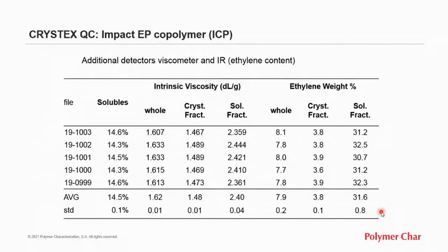As I said, in addition to quantifying the soluble fraction, the intrinsic viscosity for the whole polymer, the soluble, and the crystalline fractions are measured. For this sample, we have replicate analysis for the same sample. And we can see how the intrinsic viscosity for the soluble fraction is 2.4, which is larger than the intrinsic viscosity of the crystalline fraction or even the whole. So that may be important in some applications. And the IR detector gives the ethylene content, which is around 32% for the soluble fraction, the ethylene propylene rubber, while it is quite small for the crystalline. There's still some crystalline ethylene propylene copolymer, but very low content.